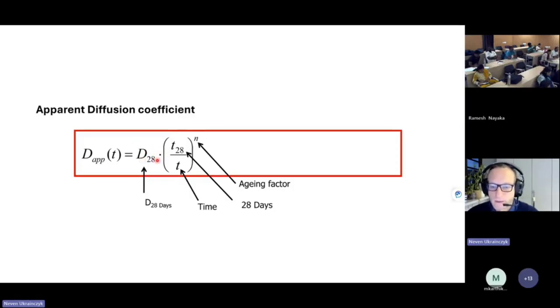But of course, you can take the chloride profile in situ, but then you can do that only when you do maintenance. If you design new concrete for bridges, you have to predict, and then you need rapid measurements. So if you make the measurements after 28 days, but nowadays they are changing this to 56 or even longer, because of more and more pozzolans inside, which are actually slowly reacting, so we need a better reference with longer